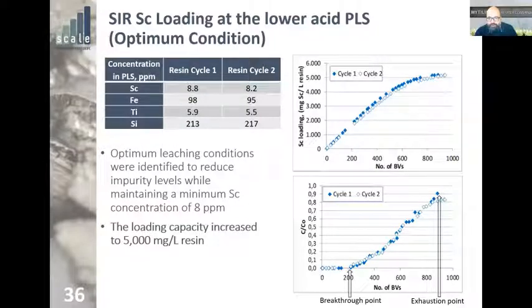So this new graph I'm introducing on the bottom right side is the relative concentration of the raffinate coming out of the ion exchange column. So we start seeing some scandium in the raffinate after 200 bed volumes, and around 900 bed volumes, the resin is no longer retaining any scandium. All the scandium that goes in goes out. So yeah, this means you can still operate. It does not mean that you need to operate 200 bed volumes.